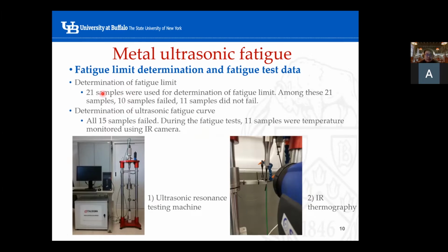We use a total of 21 samples to determine the fatigue limit, and we use another 15 samples to construct the fatigue SN curve. Among these 15 samples used to construct the SN curve, we monitored 11 samples using the thermographic camera, and the temperature recorded can be shown in the later picture.